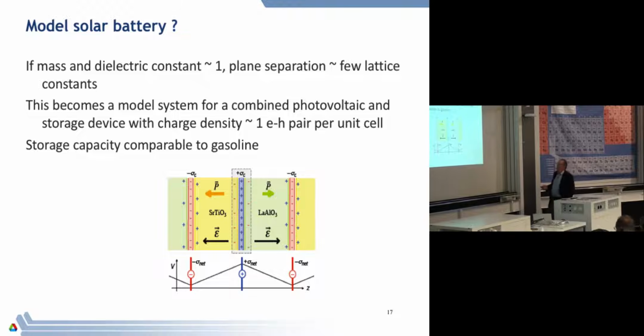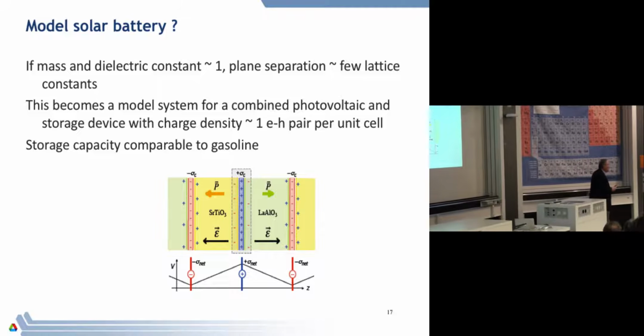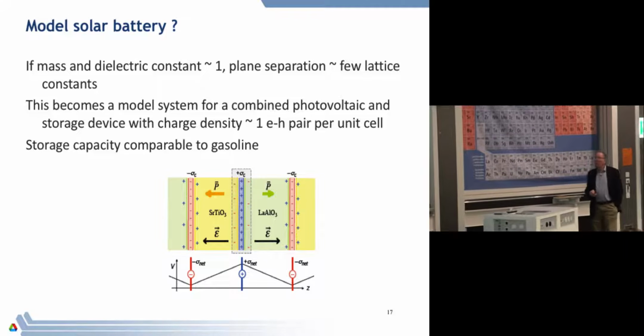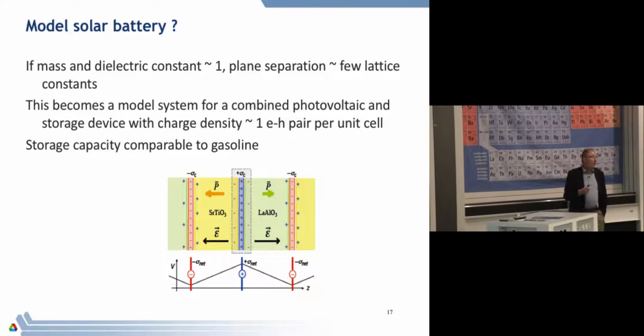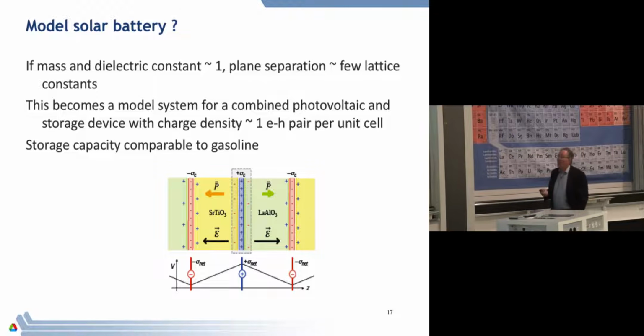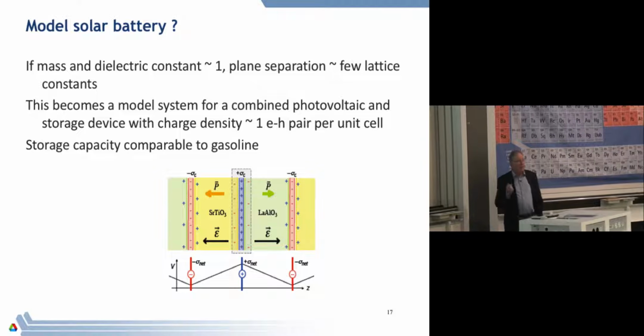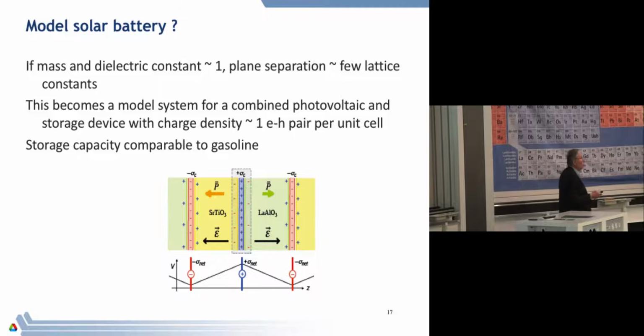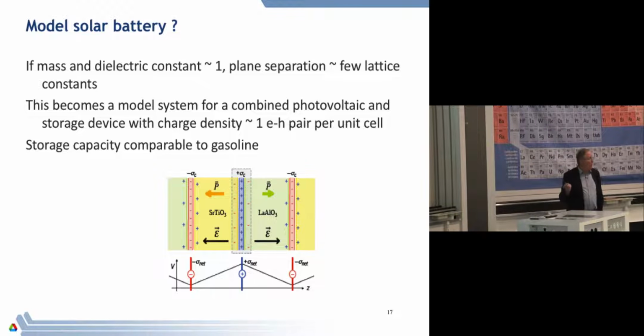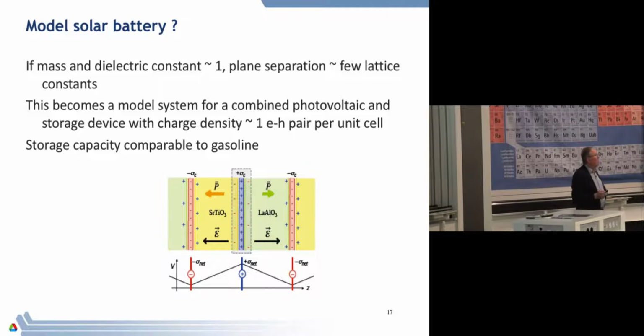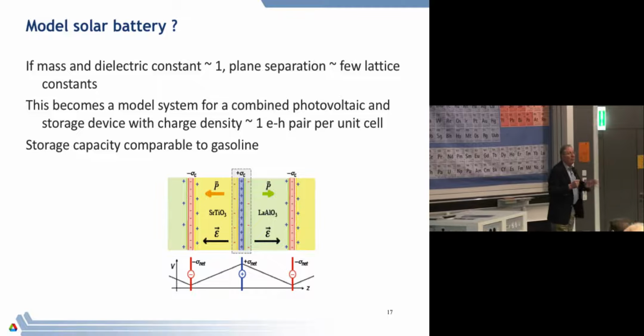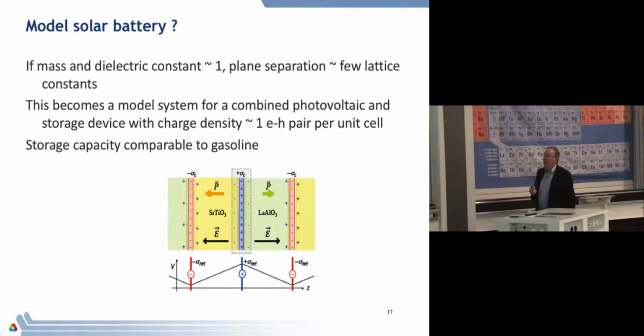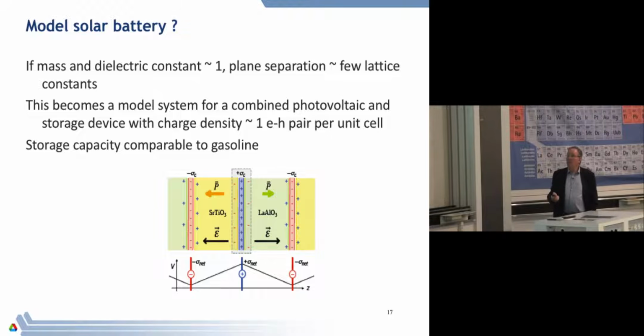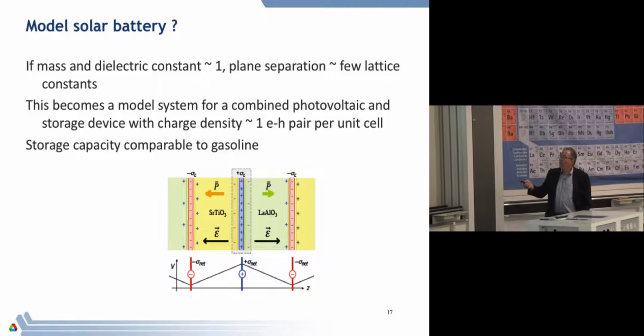And moreover, you know, the scales of the distances here are such that you should be able to charge this up almost at the level of 1 electron-hole pair per unit cell, and that would end up giving you a storage density of the order of gasoline, and so that's why it would be kind of an interesting thing to do. I think this is more inspirational about what you might be able to do than practical, because as I will point out, this sort of almost works, but not quite. Okay. But keep it in the back of your mind, because there's absolutely no reason that you should not be able to design a battery material that operates with this principle, if not these elements.